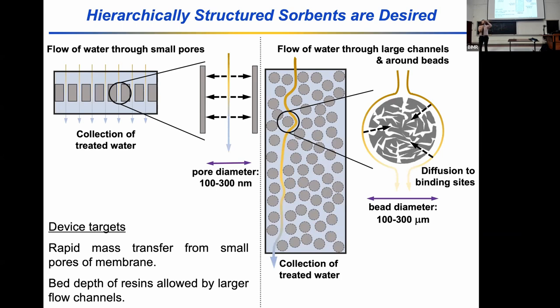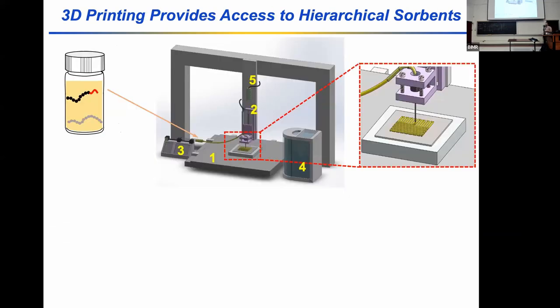And so, okay, I could stack a couple of membranes on top of each other in order to increase the capacity. But you'll remember on that first slide, throughput goes down as the thickness goes up, right? And so we'd like to find some way to get the depth of the resin beds or thicker membrane stacks at least, and the rapid mass transfer of membranes. And so what Xiaoling Zhu has been really pushing hard on is 3D printing hierarchical sorbents, where the filaments we print have the same chemistry and structure as those membrane thin film adsorbents I just talked about, but we're able to purposefully program in large channels that allow for high throughput, right?